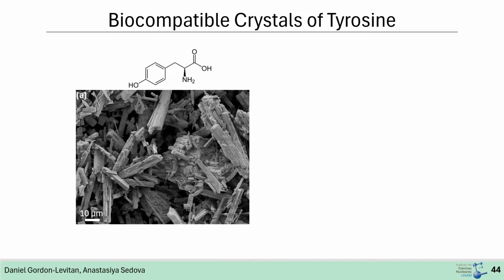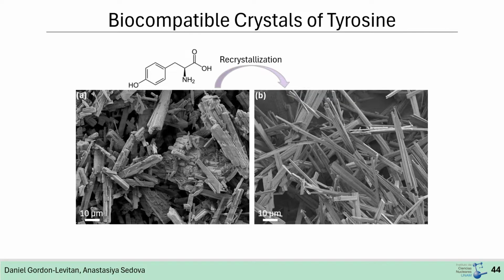And another type of materials that I'm interested in are organic crystals. It also was part of my postdoctoral experience. We wanted to use those crystals to reinforce polymers, and they use them to initiate nucleation. Nevertheless, here I want to repurpose them and use them as waveguides. So this is how we obtain those crystals from the company, and by a simple recrystallization process, we can obtain those rod-shaped particles that can be used as waveguides.